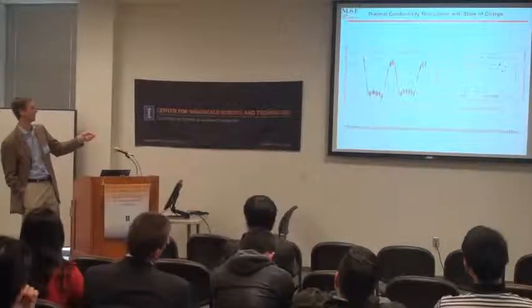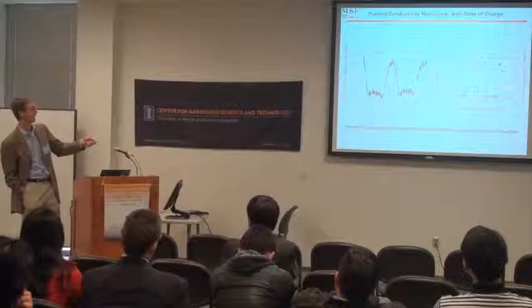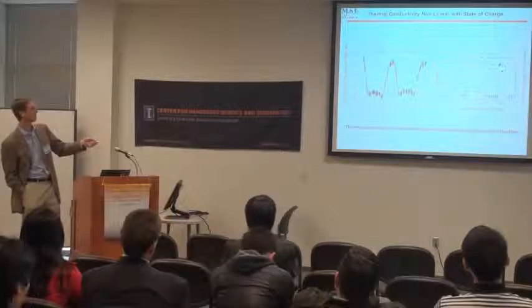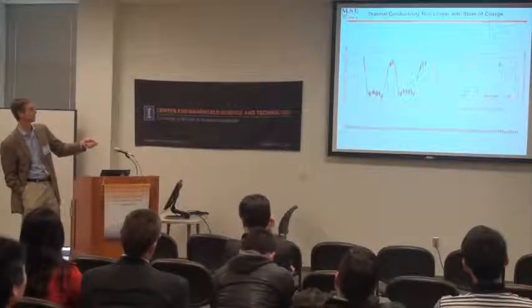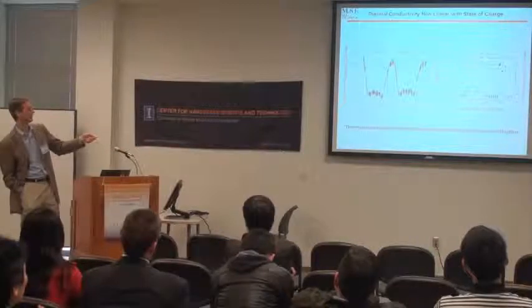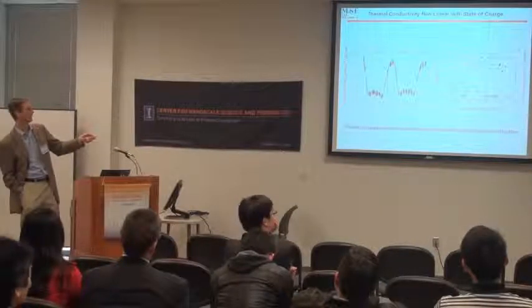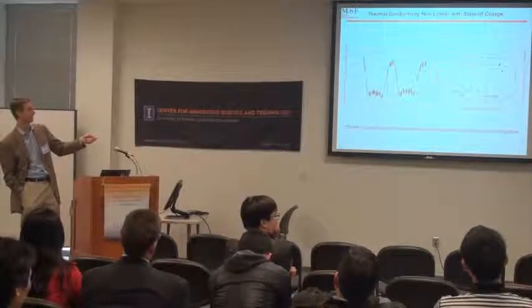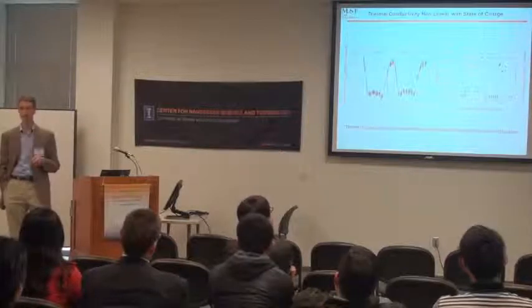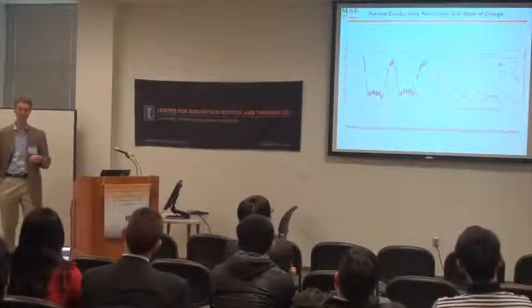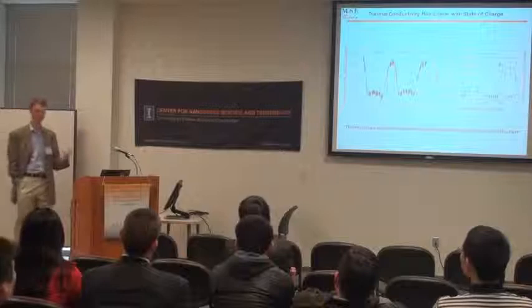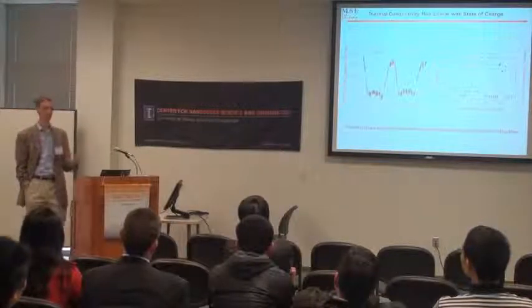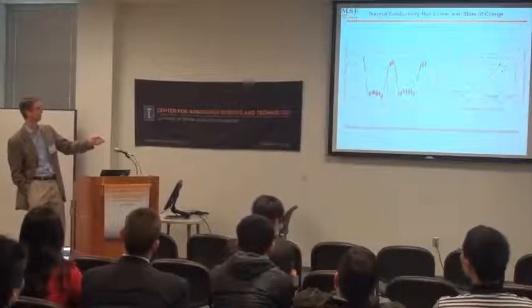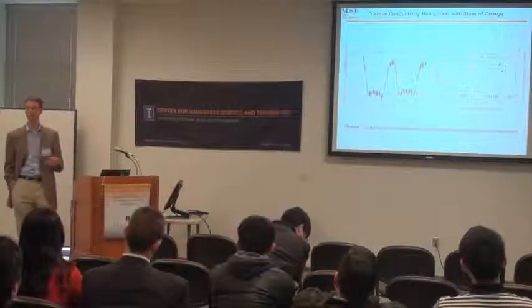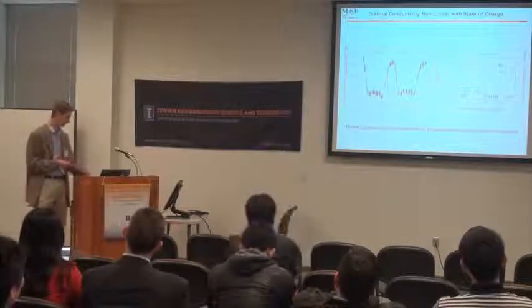As you charge the battery, the thermal conductivity first increases rapidly, and then it remains about constant. And then as you discharge it, it's about constant, and then it'll start to fall off at the end point. So I think this will be something that as heat evolution becomes more important, we're not going to be able to simply use either a linear extrapolation or just assume a constant value.